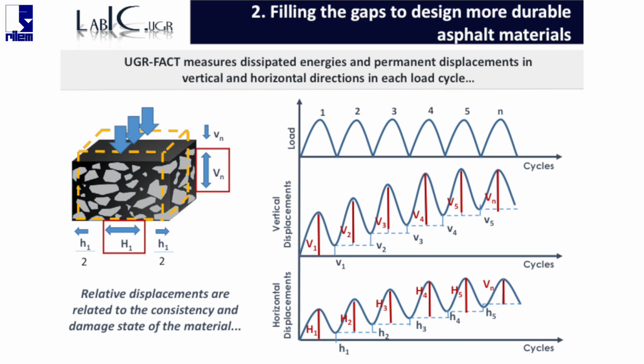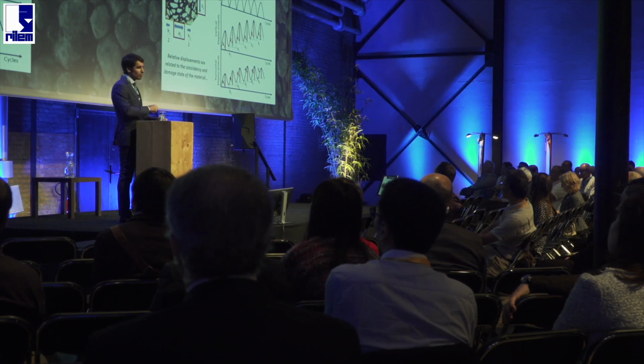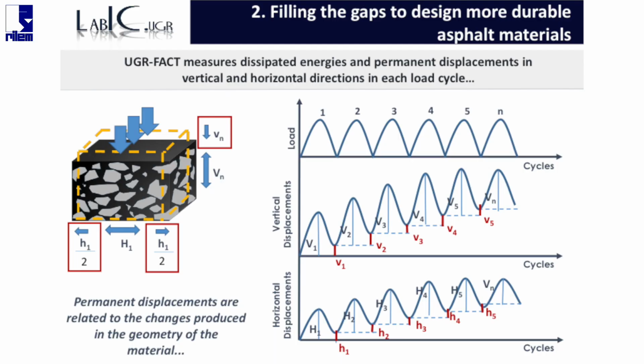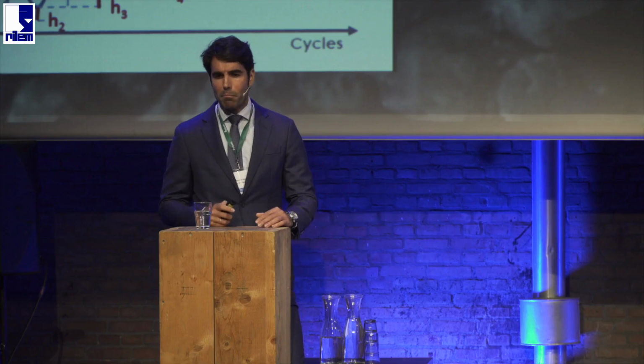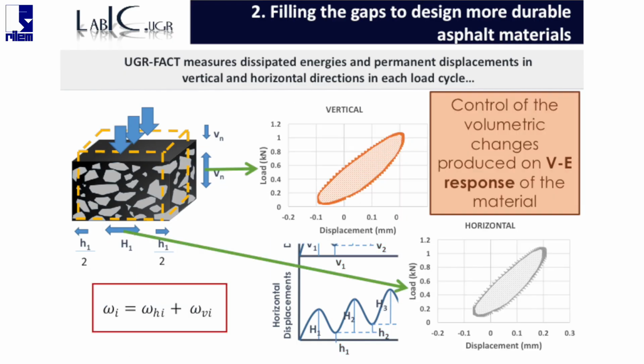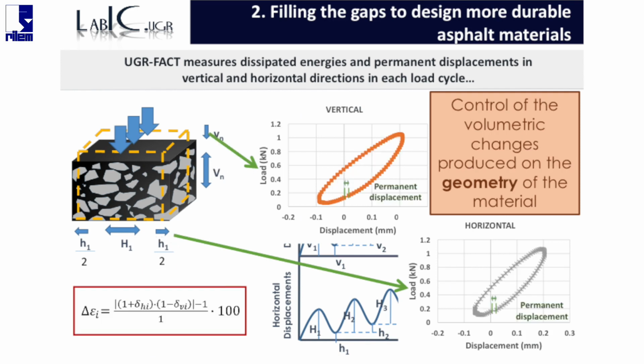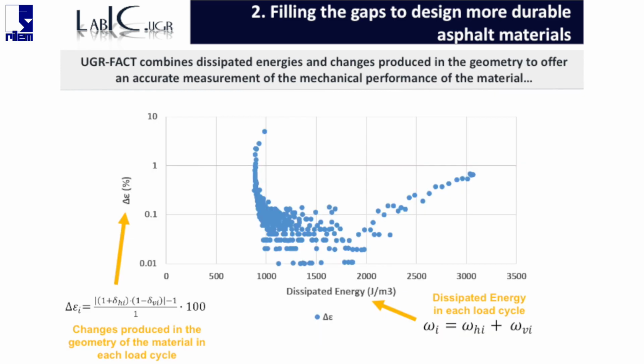These displacements are typically recorded in all types of tests and are related to the consistency of the material or the damage state. But in addition, we also record every single permanent displacement produced in the material, which are related with the change produced in the geometry of that volume. By combining both information, we can obtain a control of the volumetric change produced on the viscoelastic response of the volume, but also the control of the volumetric change produced in the geometry of the material due to the permanent deformation.